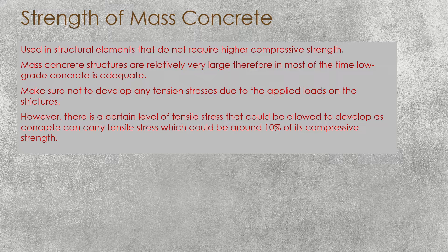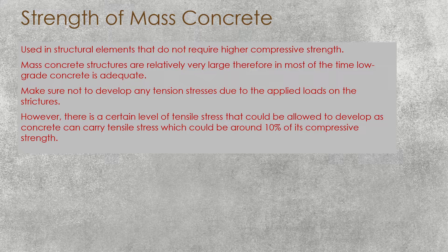We have to make sure not to develop tensile stresses due to applied loads on these structures. However, there are certain levels of tensile stress that can be allowed, as the tensile stress that concrete can carry is around 10% of its compressive strength. But usually we don't rely on that because of risks of cracking — especially in water-retaining structures like dams, where cracking could affect durability, water leakage, and permeability. In summary, mass concrete is a low-strength type of concrete.